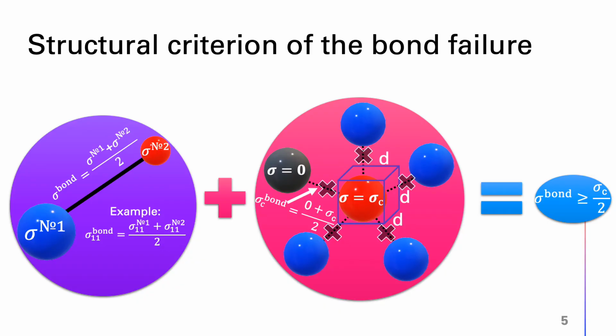In order to implement the structural approach in peridynamics, a separate failure of the bonds is considered, as for the classical failure criteria in peridynamics. Since this approach considers the stress field, it's necessary to introduce the concept of the bond stress, which in this work is assumed to be equal to the mean value of the stresses in the interacting elements, as some other authors have already done. By sigma, any component of the stress tensor is meant. For example, the stress component of the bond, sigma 11, is equal to the sum of sigma 11 in the first particle and sigma 11 in the second particle divided by 2.